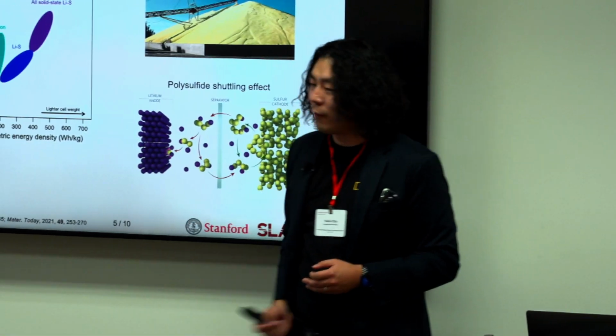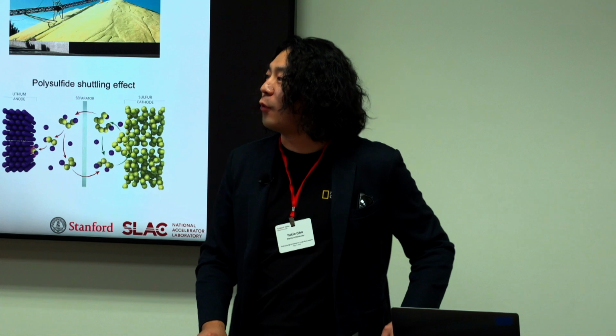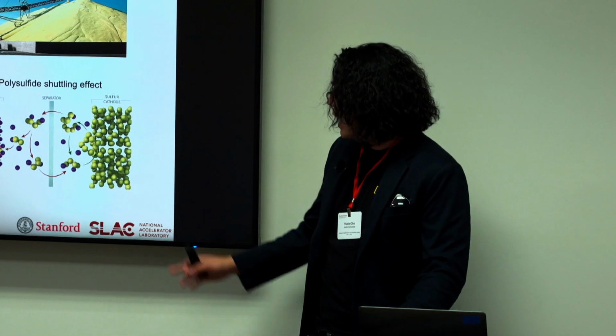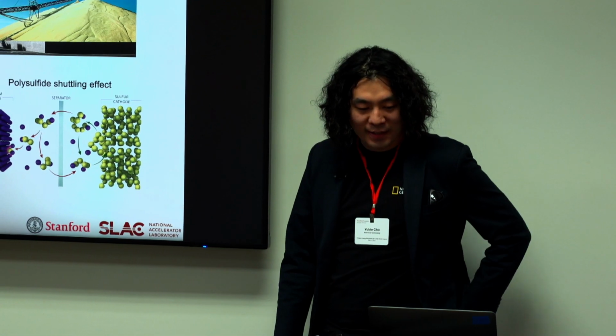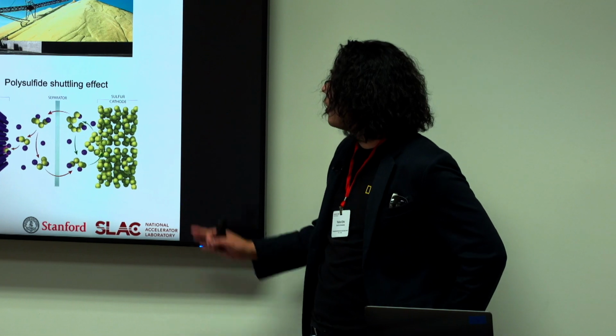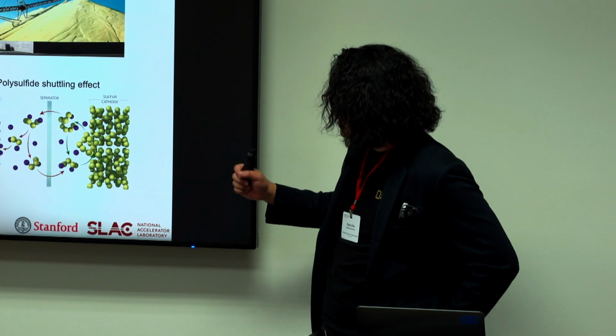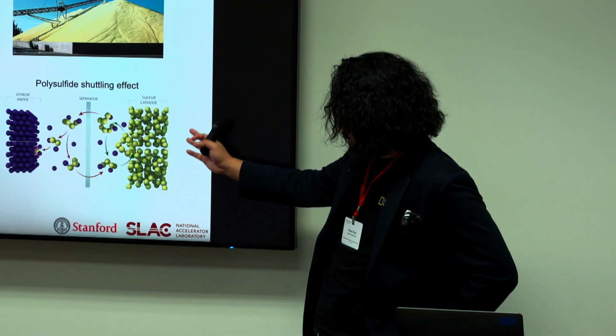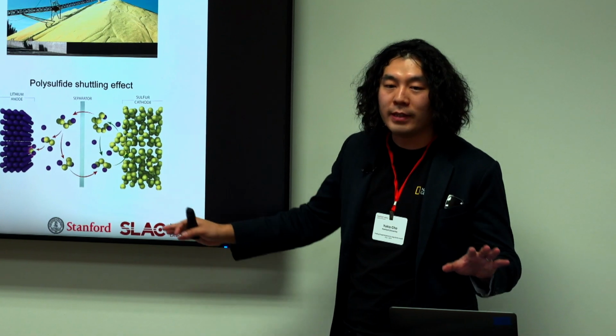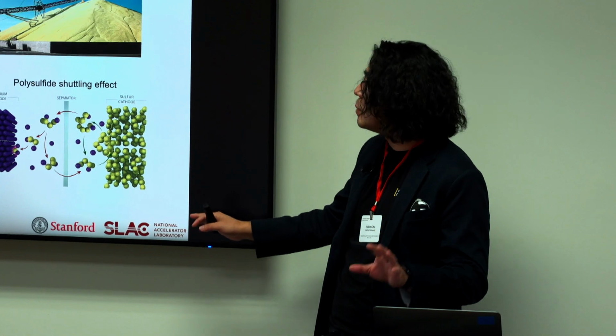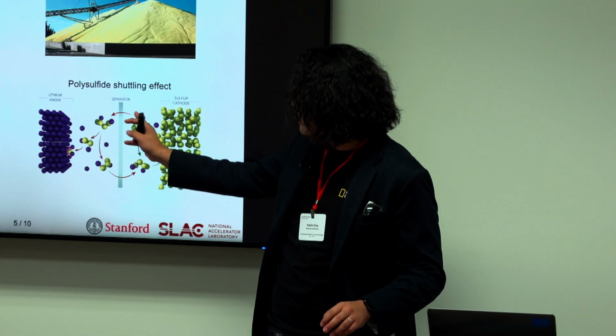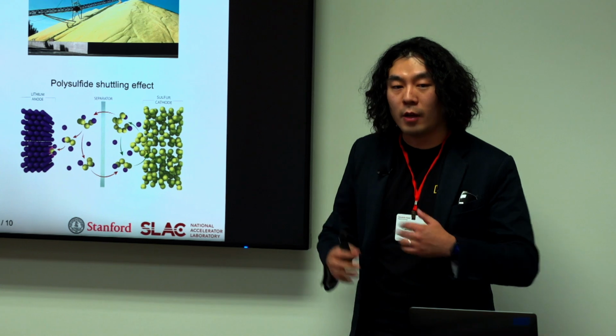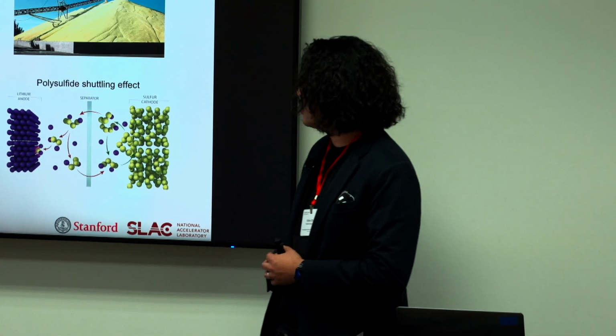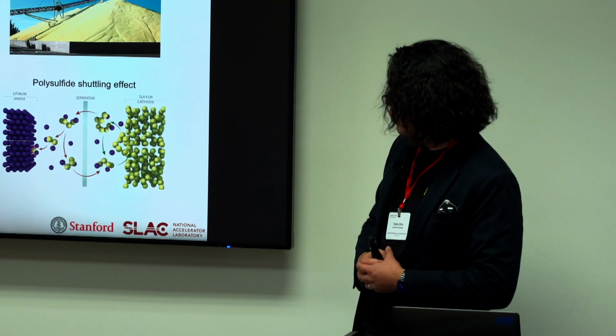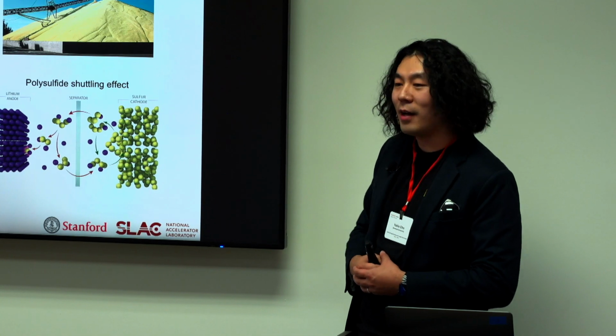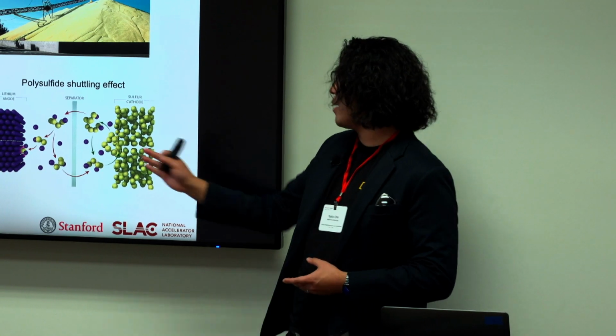Nevertheless, lithium sulfur battery researchers have been combating for about 30, 40 years a main issue called the polysulfide effect, a shuttling effect. What's happening here is that the sulfur, the yellow part, will start to move around when it chemically reacts to the intermediate state. When it moves around, it comes to the other side of your battery, and your battery starts to degrade. We have been fighting this for 30 years, and we still have not come up with a conclusive idea to preserve this.